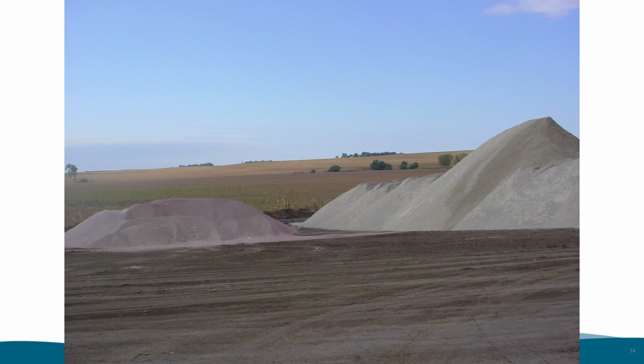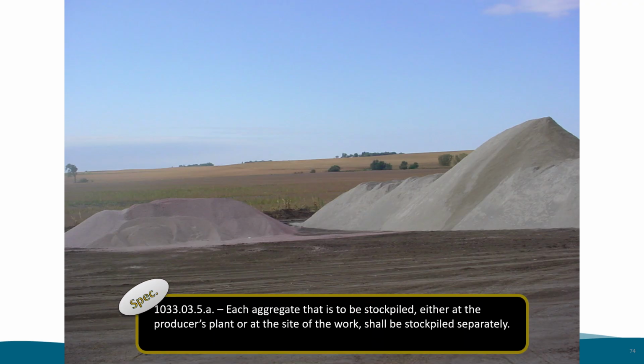The aggregate has been produced. Now what? Let's talk about stockpiles and best management practices. It's imperative to keep stockpiles separate. Aggregates are typically piled into an arc to reduce segregation. Care shall be exercised to avoid segregation and degradation of aggregates or the inclusion of foreign material in the aggregates while the aggregates are being removed from the stockpiles. As written in the standard specification, each aggregate shall be stockpiled separately.